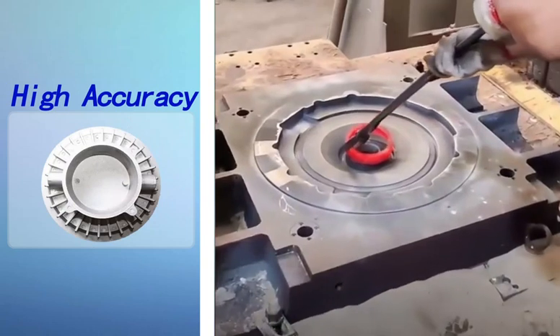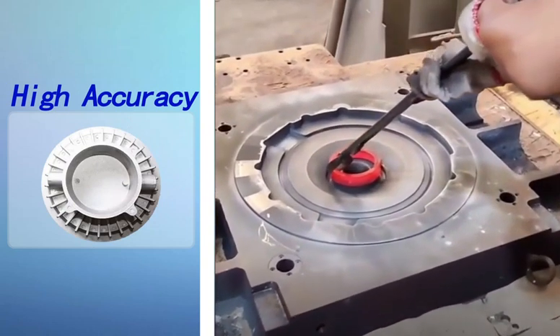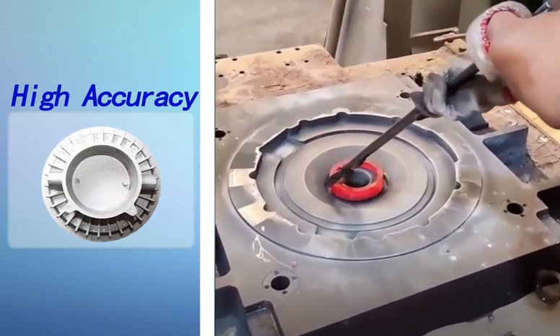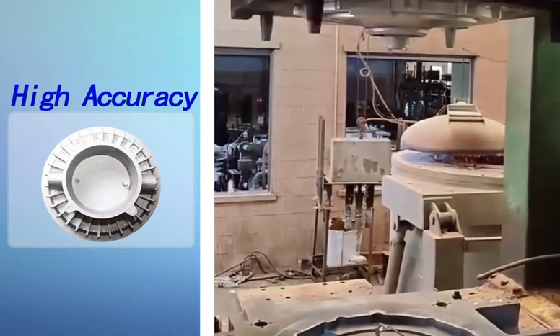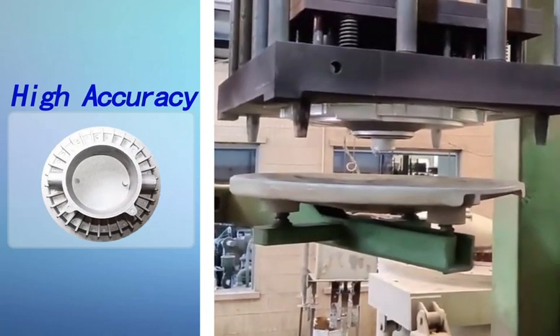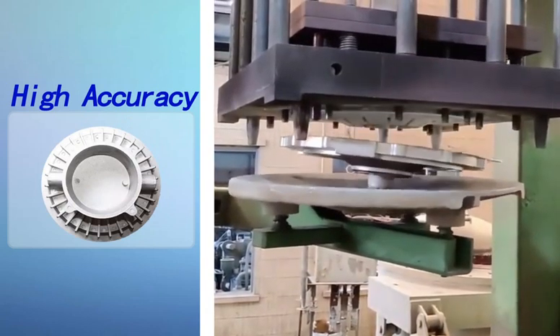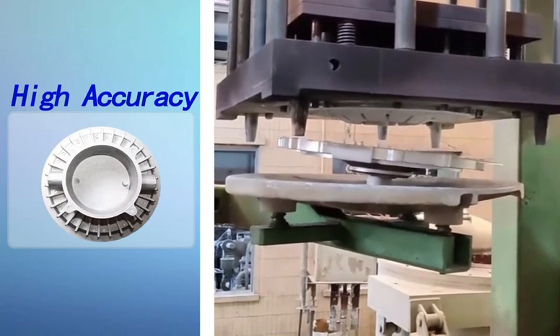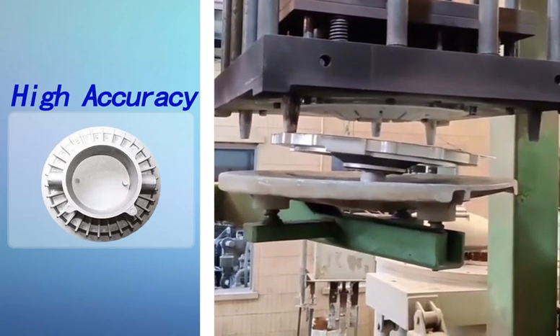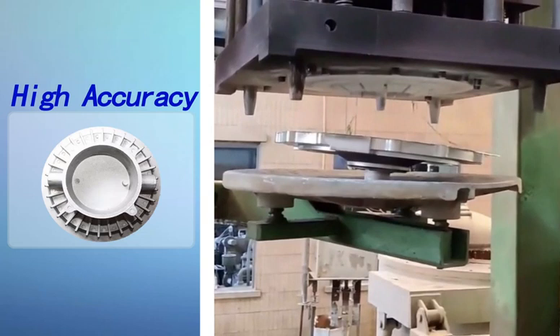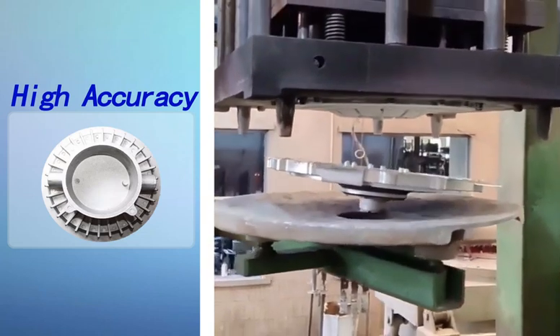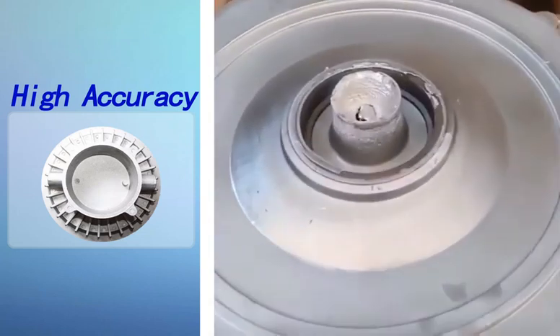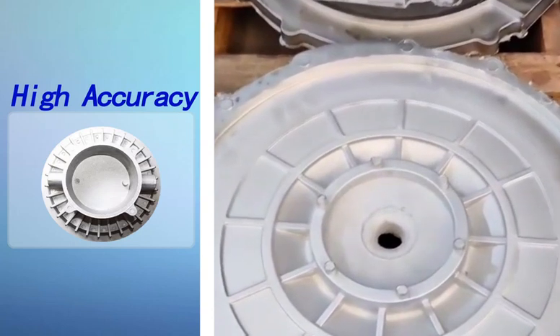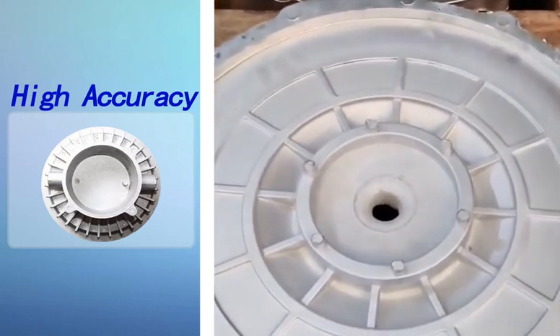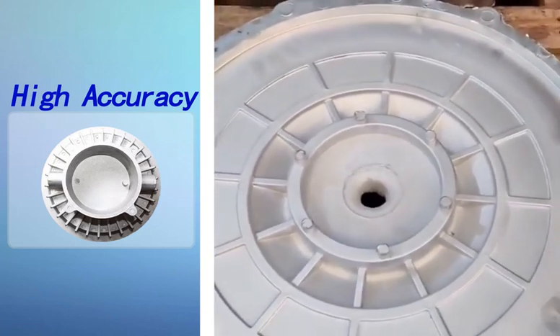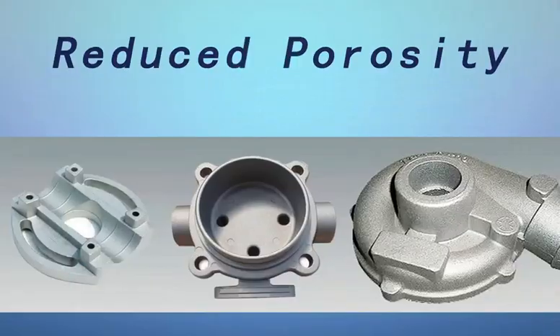High accuracy. The precision of parts produced through low-pressure die casting is attributed to the maintained low pressure during solidification. The low pressure allows for the continuous filling of the die cavity, compensating for any shrinkage in volume as the molten metal solidifies. As a result, the process is ideal for manufacturing axially symmetrical parts such as wheels, where high accuracy is crucial. Reduced porosity.